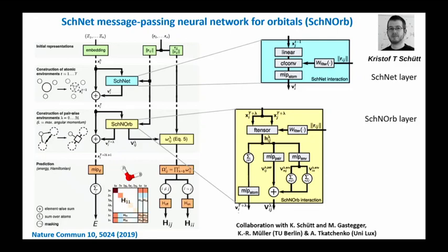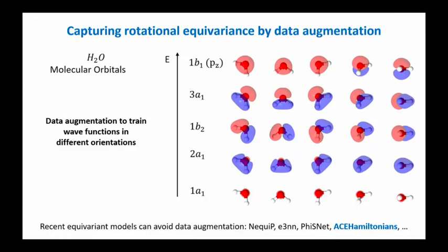And the one thing you need to remember is that all of this falls apart if you forget this bit here. So instead of just looking at all the possible distances in the system, we have to look at directional distance vectors. And the reason for that is, of course, that atomic orbitals have a phase. So it matters if my p orbitals look like this or like this, because if I don't include the actual sign that relates them orientationally, I cannot describe the way two s orbitals split up into a sigma and sigma star when they come together. So it really, really doesn't work. If you train this model on Hartree-Fock, DFT data, mean field Hamiltonians in this local orbital representation, you can see you can represent the orbitals.